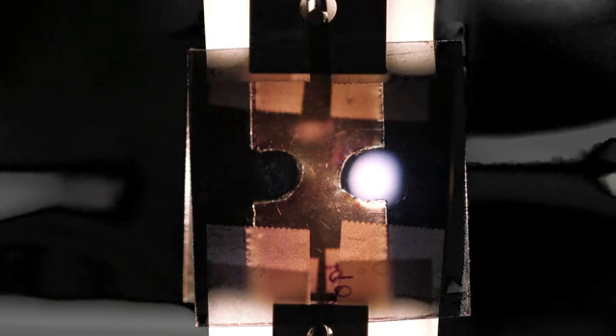So what we have here is just a piece of plastic with a rounded notch. And in the engineering world, we like rounded notches as opposed to really sharp notches, because the smoother you can make a transition, the better off you are, and the less of what we call a stress concentration you have. So let's go ahead and stretch that piece of plastic. We're going to wait for the machine. It has to engage a little bit. There are some pins up top, and here we go.